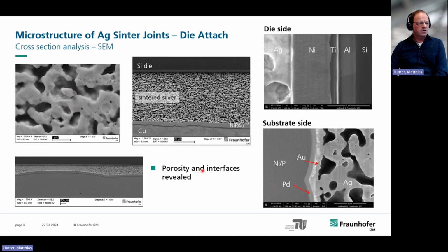Of course, cross sections are also very important because the focused ion beam method is quite expensive, and it is only applicable on a very tiny scale. It's not so easy to prepare these samples. You need to apply proper preparation methods, and if you do so, you can really reveal the microstructure, the porosity, the interfaces. Here you can see the interface on the die side, so the silver with a direct interconnect to the die metallization. And here on the substrate side, you see interdiffusion shown here. You see that the gold partly really diffused into the silver here.